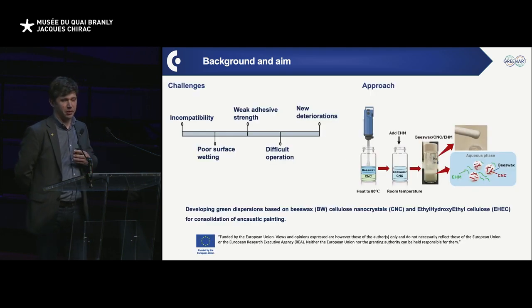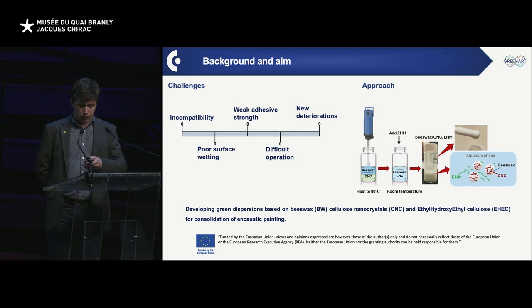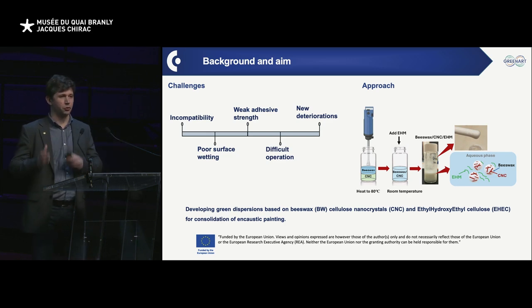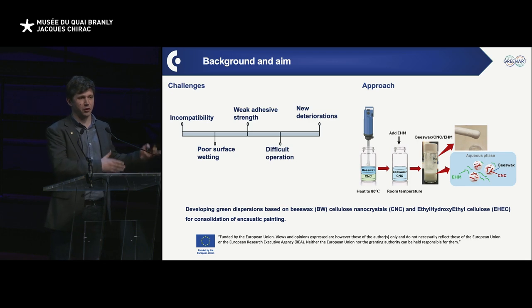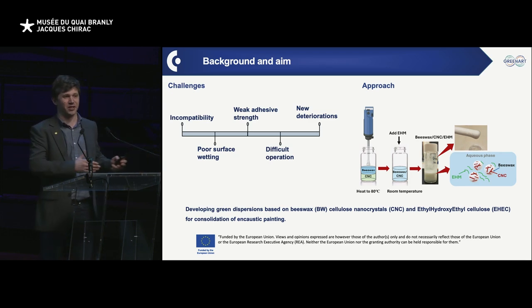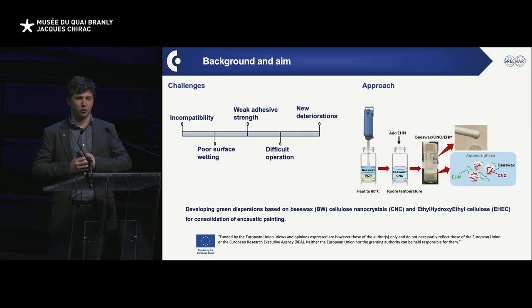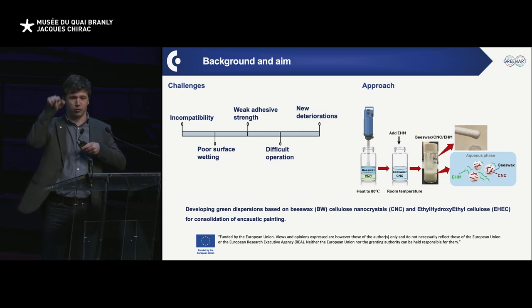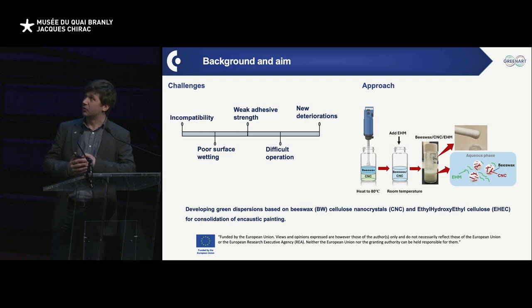So with that in mind, we had to sort of face the challenges of incompatibility. Having a decent surface wetting, we need to make sure that when we apply the stuff on the surface, we will wet. And one of the challenges, you want to make it green, working with water. Water is bad at wetting anything but paper, essentially, I would say, especially encaustic painting and beeswax. Water is not good at wetting beeswax. The droplets do not spread. It will remain on the surface. We need to have a good adhesion to overcome this weak adhesion issue, and having an ease to operate the system and avoiding new deterioration.